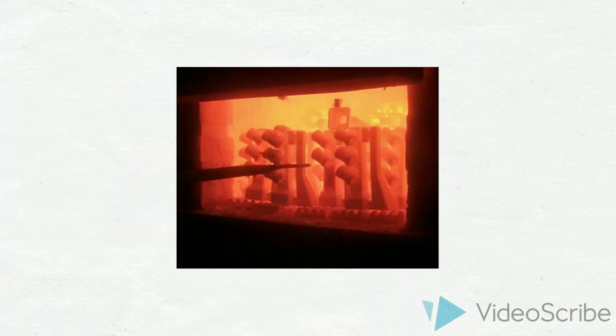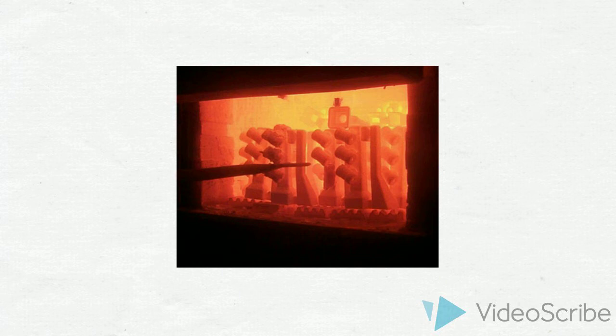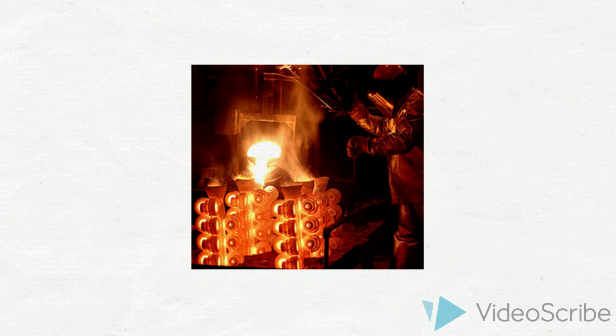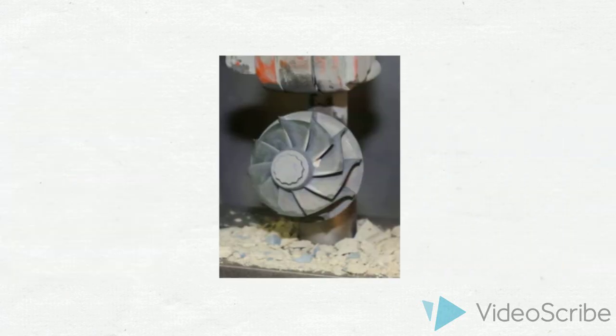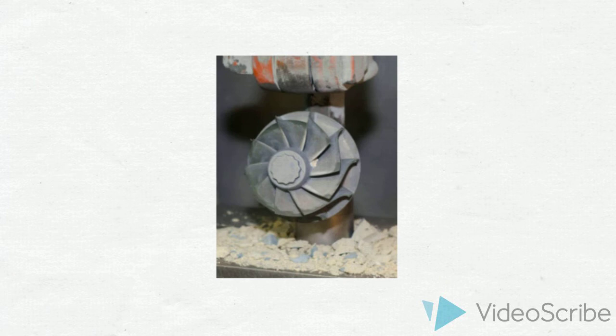The molds are grouped by like alloys and fired. Metal is then melted and poured into the mold. After pouring, the mold is allowed to cool and the ceramic mold material is knocked off. At this stage, we can now see that what we had in wax is exactly what is now metal.